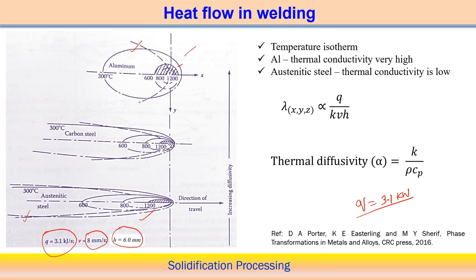Here, just as an example, this temperature isotherm is represented by 600 degree centigrade, then 800 degree centigrade, and 1200 degree centigrade. Just tracking the temperature isotherms, if you plot the melting point temperature, or solidus or liquidus temperature, the zone within the melting temperature is identified as the molten pool. If I assume 600 degree centigrade for plain carbon steel, a kind of phase transformation occurs. Therefore, between 600 degree and 800 degree, or maybe between 600 to 1200 degree centigrade, that indicates the heat affected zone.